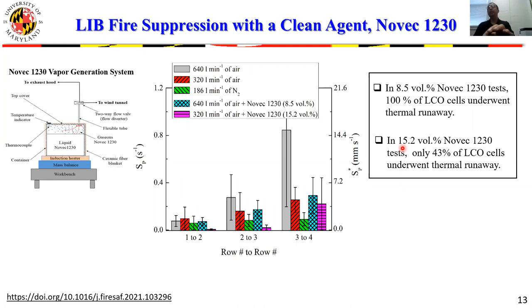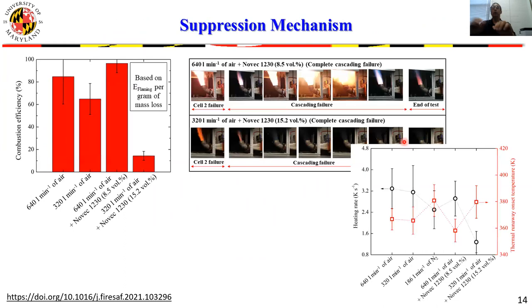However, at 15.2%, we found Novec 1230 to be highly effective. We found that the combustion efficiency inside the tunnel was brought almost to zero, right? So about 15% on average. So we suppressed pretty much all flaming combustion in multiple tests. We also found no indications of reignition in this test.